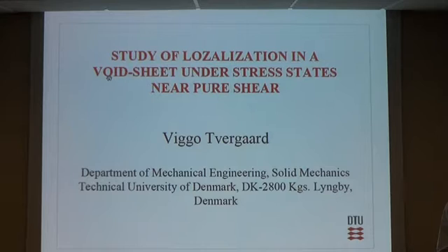Let's see. Here's one of the cases. It's still for pure shear. You see that the initially round voids have here collapsed towards a microcrack. Here it has become a microcrack. There is a width, but that's because of a pseudo method for making the contact. The rather strong contact develops here, and you see clearly that the void has rotated a little. It's rotated in this direction. That means phi has gone from 90 degrees to a smaller value, and is still going smaller here where the contact has just started.